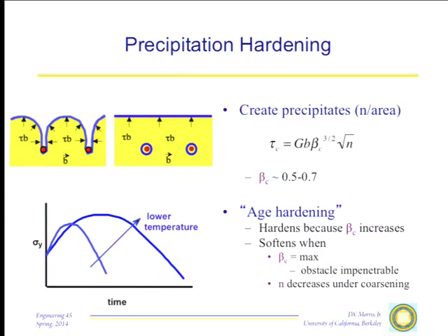So if I just look at the phase diagram, any typical phase diagram, the lower in temperature I go in my aging, the higher the fraction of the precipitate phase. The lines that border the phase diagrams always slope toward the boundary. Go to lower temperature, you get a bigger fraction of precipitate, meaning you get a higher hardness. The problem is that precipitate coarsening is governed by diffusion. The lower I go in temperature, the higher hardness I get, but the longer time it takes me to get it. And the actual age hardening treatments that are used are optimizing the trade-off between these two factors.